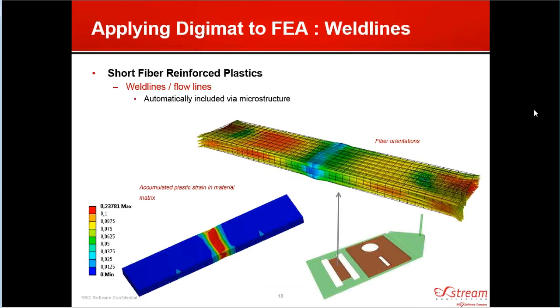So one of the most important things about this approach is that it allows you to take things like weld lines automatically into consideration. So the areas where you have these weld lines, you'll have these little balls of randomly aligned fibers from the two flow fronts meeting, and in those areas you'll see this reduction in stiffness and reduction in strength that typically comes along with a weld line.